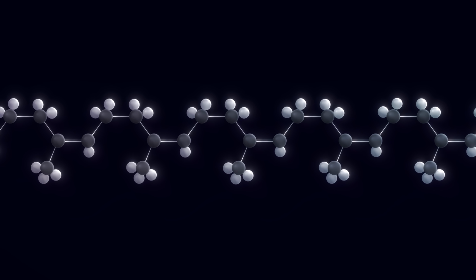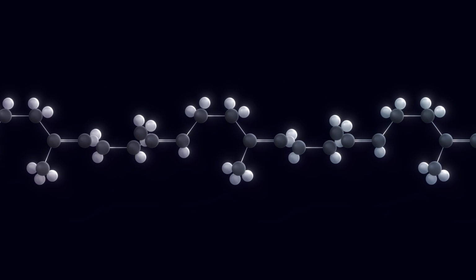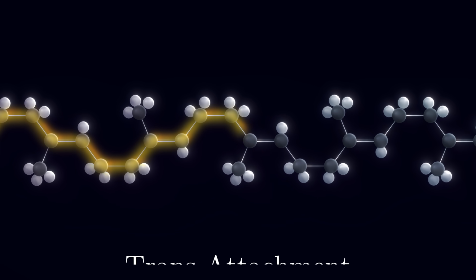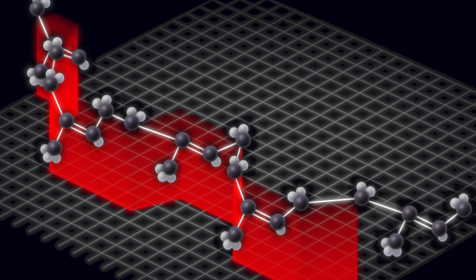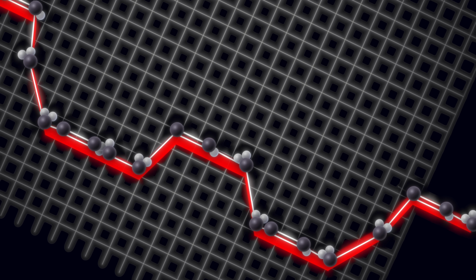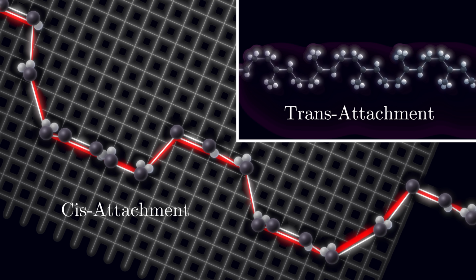But with synthetic rubber, it's easy for monomers to attach on the opposite side of the double bond. That's the trans attachment. But now there's more room for them to lay flat. They don't have that extra wiggle, so they stretch less and don't crystallize very well. And when you make the synthetic equivalent, it's pretty good, but it's 98% cis polyisoprene. There is, 1 or 2% is going to be trans polyisoprene, and therefore isn't so susceptible to crystallization, and it's not as good and hasn't got the same strength properties that natural rubber would have.